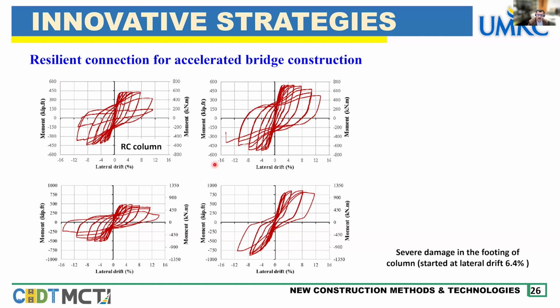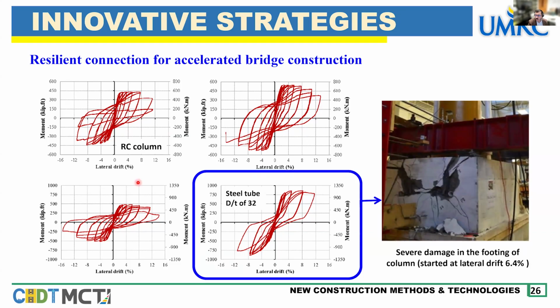So as you can see from the hysteresis curves for the tested columns, one of the columns with the D/t of 32, and here the steel tube was 0.5 inches thick. As you can see, there is a huge pinching effect here. And we achieved the high strength, but not the required fat loops, which are very important for energy dissipation. And with this column, the connection, as you can see here, failed progressively because of the severe damage. This initiated at a lateral drift of 6.4 and propagated, as you can see, to this picture here.